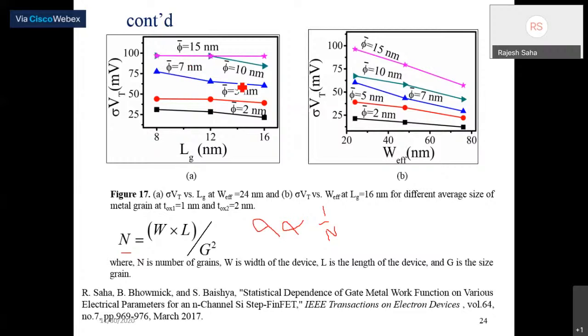However, for various grain sizes we have observed this. Similarly, if the grain size increases, then what will happen? N reduces. If grain size increases, n reduces, that means the variation in the threshold voltage increases. However, as you can see, when the grain size is 15 nanometer, it becomes almost constant.